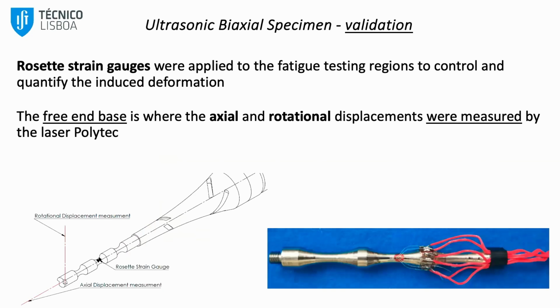These studies on FEM, and we have also applied some strain rosettes in order to measure the strains in the main throat here in the middle, and at the free end base we have measured with the laser Polytec the displacement and the rotation of the specimen in order to validate our simulations, our numerical simulation.